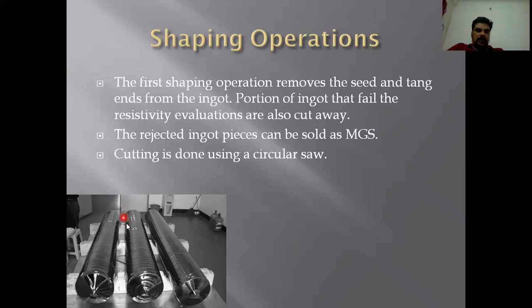There is also the seed end, because you have seen in the seeded process that we used a seed crystal on which the silicon was grown. So that is the seed end and this is the tang end. First of all, these two ends are removed. Now in this process, there are also certain resistivity tests. In order to measure the resistivity, the portion of the ingot that fails this test is also cut off. These rejected ingot pieces can be used as metallurgical grade silicon, and from that we can obtain electronic grade silicon by repeating the same processes that we discussed in previous lectures.